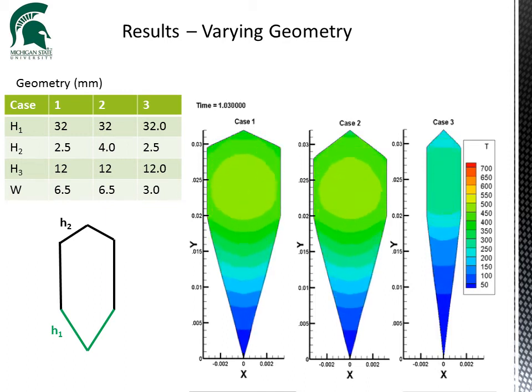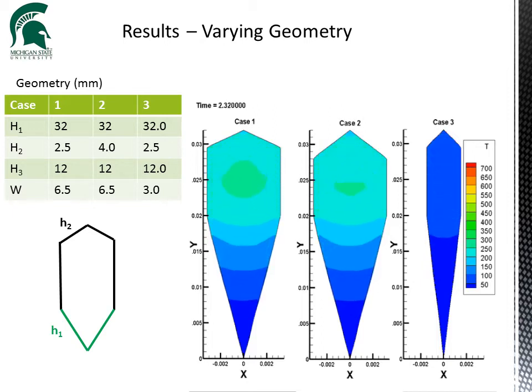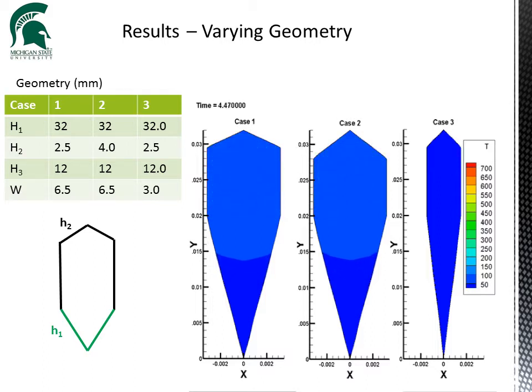And so, as you can see, by changing the height dimensions, there is not a significant change in the temperature distribution or the rate of cooling, while the thinner cross-section has a much more rapid cooling rate. And so which results in a lower quenching time, and so you'll want to pull that sword out of the bath much more rapidly than in the case of a thicker blade, just due to the rate of cooling.